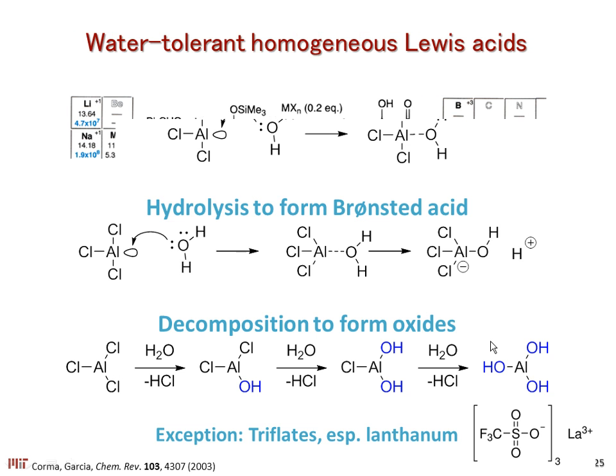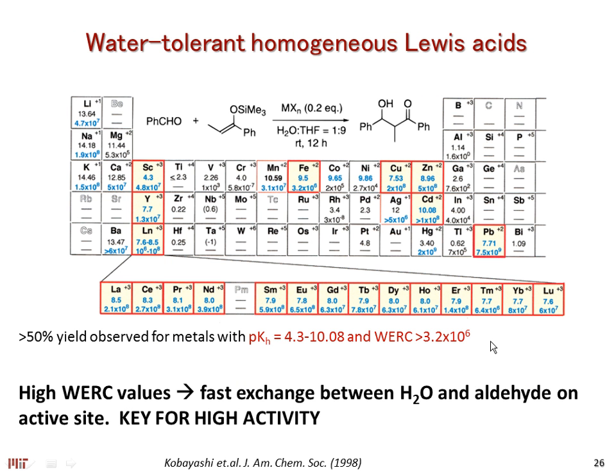Without going too much into the details of why this is the case for these particular salts, this paper by Kobayashi, who worked a lot on these triflate salts, tried to understand why they were able to withstand water. There are a lot of different effects. One of the most important ones is what is called the water exchange rate coefficient, and it's pretty much a measure of how quickly water comes in and out of the coordination shell around these Lewis acids. What they found is that as long as this exchange rate was very fast for a particular metal, the metal would be able to maintain activity even in the presence of water, which means that they are able to bring carbonyl functional groups or oxygenates or different electron-bearing functional groups into the sphere